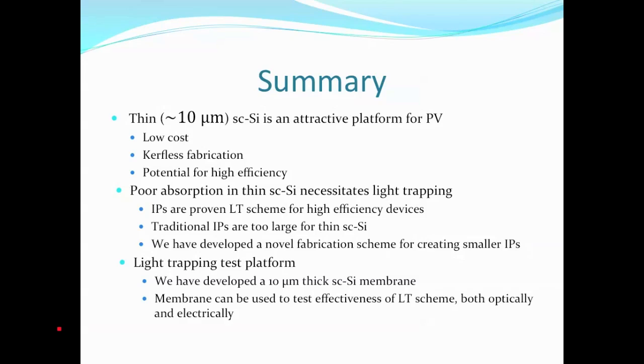Standard inverted pyramids are not useful for light trapping, so we use smaller inverted pyramids. And finally, we implemented these inverted pyramid textures onto a light trapping test platform that's 10 microns thick. That can potentially be made thinner.